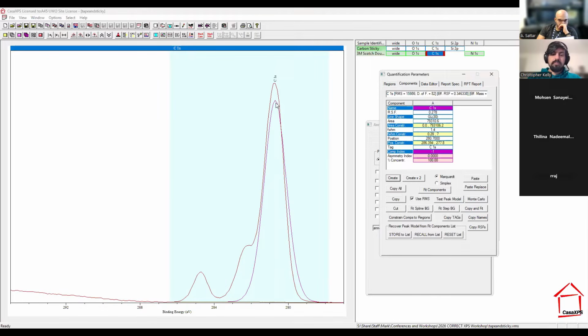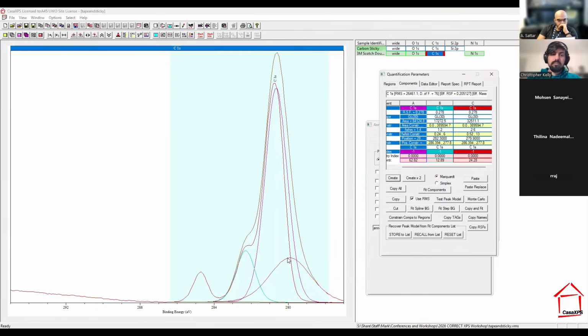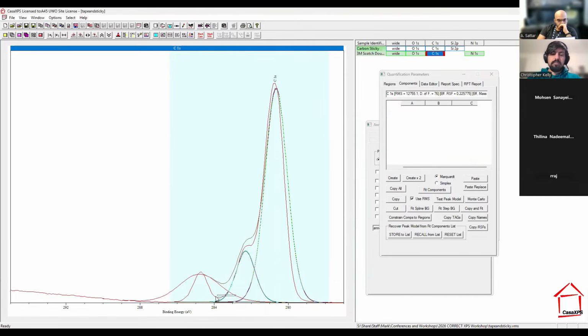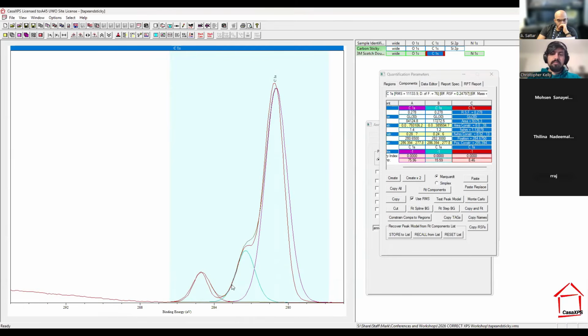And so we have a peak at that starting one. Obviously, that doesn't cover all the area under the curve, so we'll create another peak and maybe one more for this peak over here. We can change that full width half max. And if we do a simple fit, already we've got a pretty good fit of that peak.